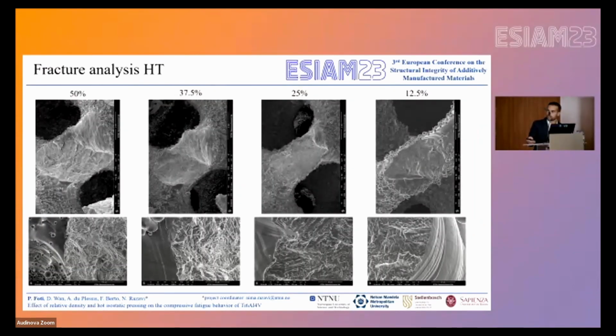Here you can see the fracture analysis of just one strut, and as you can see, it's not possible to notice any difference between the different relative densities. Of course, we reported just the fracture surface of the annealed samples, but with regard to the annealed and HIPped samples, no significant difference has been noticed. And as you can see here from this magnification, the failure always started from the surface in correspondence to the nodes.